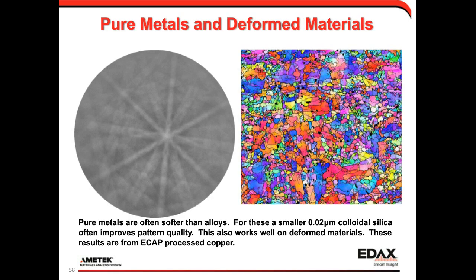This is just an example from a pure metal. This is pure copper. In this case, it's softer than an alloy. It's a little bit more susceptible to surface smearing and deformation. So in this case, I've used a 0.02 micron colloidal silica, and that generally works pretty well.